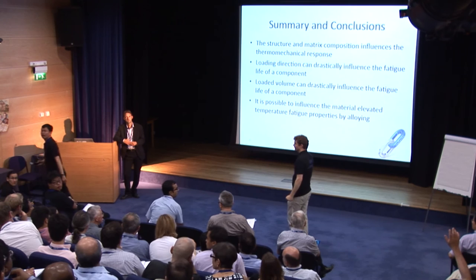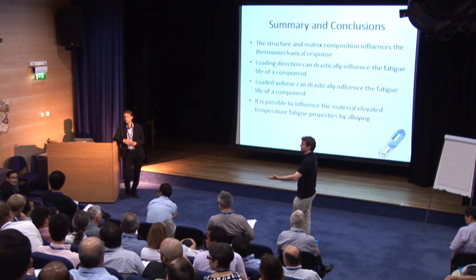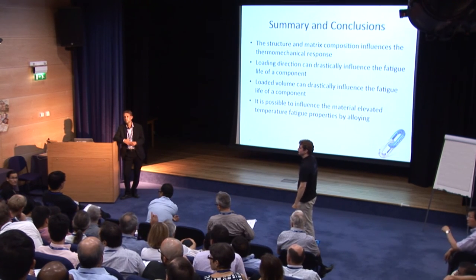Okay, one question: why did you choose the temperature you used for the rolling contact fatigue test, 100 degrees? And have you performed any rolling contact fatigue testing at other temperatures, including room temperature, and seen what the difference is? We have a fairly simple rolling contact fatigue flat washer test machine, and we have looked at the temperature, and you can clearly see an influence of temperature on the material decay in rolling contact fatigue.